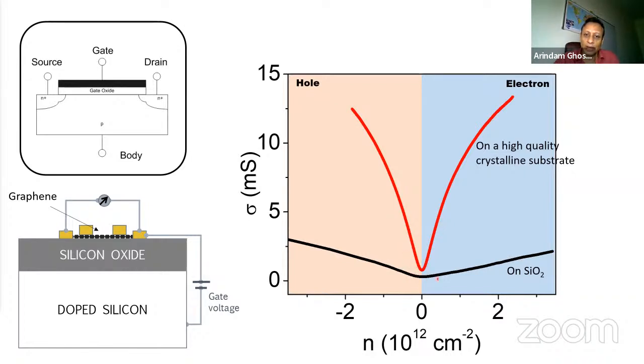It turns out that one is on silicon oxide, which is usually a very dirty amorphous substrate, whereas the red one is when you keep the graphene on a very clean single crystalline substrate. That time you get a much larger electrical conductivity. The reason behind it is that the electrical conductivity is directly proportional to what is called the electrical mobility of any charge carrying system. Sigma is equal to the electronic charge multiplied by the density of carriers multiplied by the mobility of the carriers. And the mobility tells you how fast a charge moves from one end of the sample to the other.